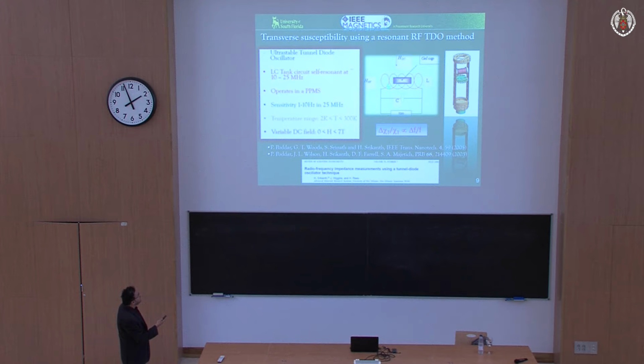You put the sample inside there, and the transverse geometry is because of the perpendicular fields, the DC field, which is generated by a superconducting magnet, the PPMS, for example. We put the whole system in there like this. And then the transverse geometry is because the DC field is perpendicular to the small modulating RF field, the high frequency field. The transverse configuration is not very strange because that's what is used in FMR, ferromagnetic resonance, where you have these crossed fields, and also in NMR. Okay? And what we do is we just put in a frequency counter and measure the shift in the frequency, and from that we extract the change in the so-called transverse susceptibility. In the next minute, I'll explain to you why we do it in this transverse configuration.